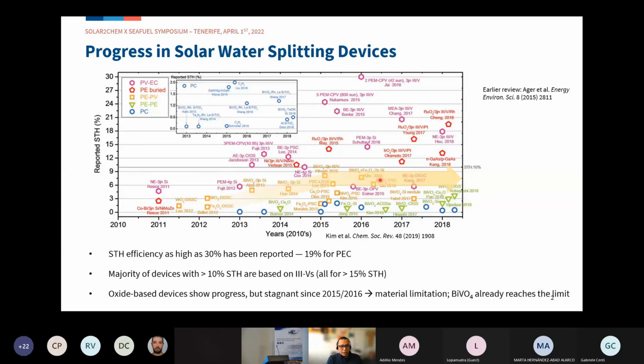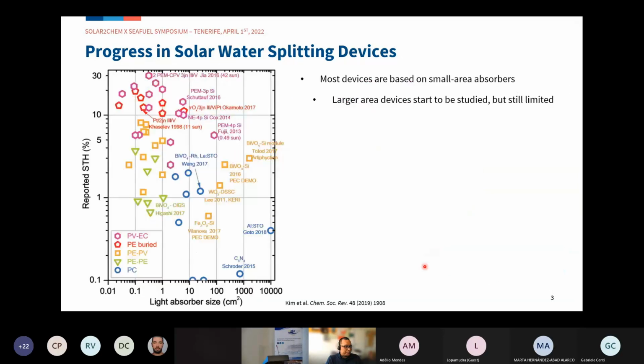And this is caused by material limitation because, for example, bismuth vanadate, one of the materials that's used a lot in these demonstrator devices, has actually already hit the limitation. So the performance is already very close to the theoretical limit. That suggests that we actually need novel complex oxides if we want to push the performance of this type of devices further. And indeed, that is actually what we are also working on in our institute and in my group. But this is not what I'm going to discuss today. Hopefully, in another opportunity, we can talk about this.